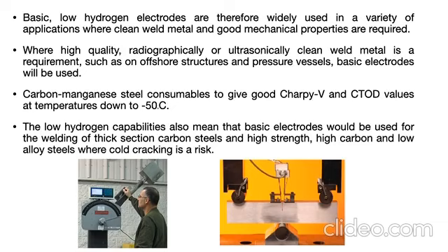During this time, the hydrogen which is already present inside due to the solubility at high temperature may not escape out due to the sudden change in temperature. So at room temperature or at a reduced temperature, the metal will be in a supersaturated condition of hydrogen. So the hydrogen will always have an affinity to go out, because it is in a supersaturated state.